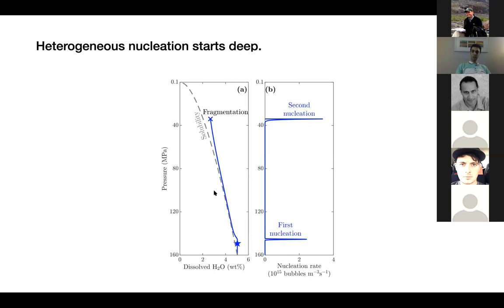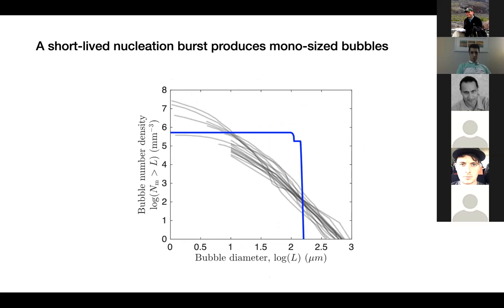Throughout the ascent, water remains close to equilibrium. However, at some point, it again starts deviating from equilibrium, creating another supersaturation pressure, resulting in a second nucleation right at fragmentation. Nucleation in heterogeneous case just starts deep, but nucleation occurs over two very short-lived bursts where bubbles basically all nucleate together and grow together at each individual event. This results in bimodal bubble size distributions as shown here.